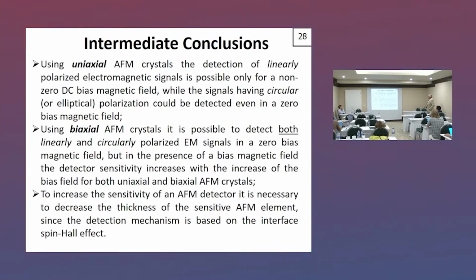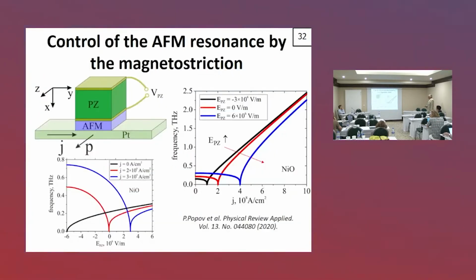So the intermediate conclusion is that if you want to have a receiver which will work with signals of any polarization, you need to use biaxial antiferromagnetic crystals, and you will increase the sensitivity of a detector if you apply the external bias field. What you can do also to change frequency is to put the antiferromagnet in contact with piezoelectric. In that case, by applying electric voltage to piezoelectric, you can change anisotropy in the antiferromagnet, and you can change the frequency of antiferromagnetic resonance.